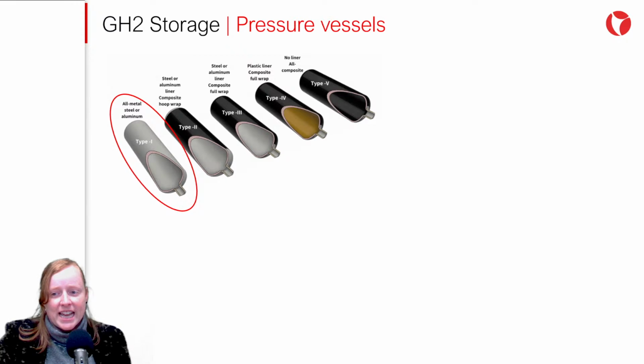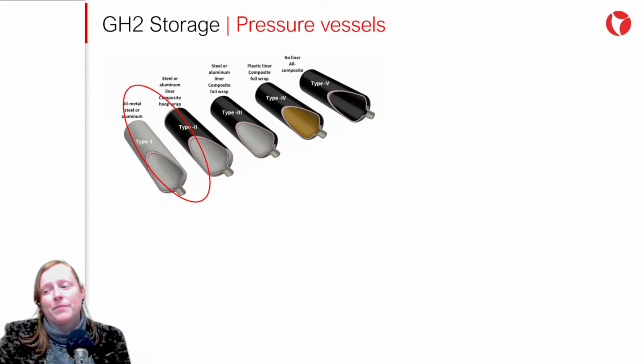Tanks built according to ASME Section 8 Division 1 typically have a maximum pressure of 200 bar. However, tanks built according to Divisions 2 or 3 can operate at pressures of up to 1,000 bar and even higher. The mass of metal required to contain the pressure in a Type 1 tank generally allows for only 1 to 2% hydrogen storage relative to the mass of the cylinder.